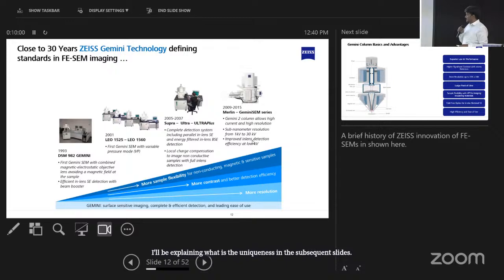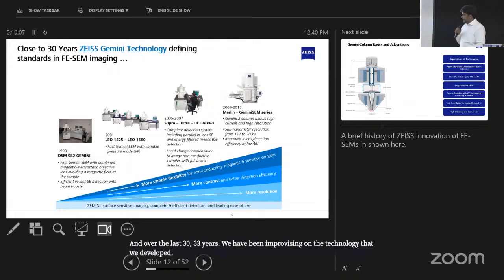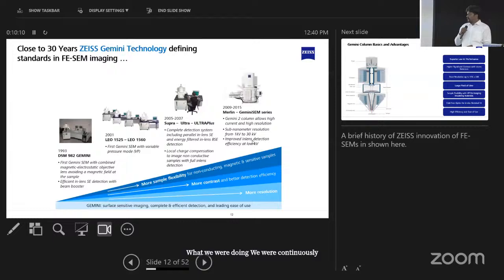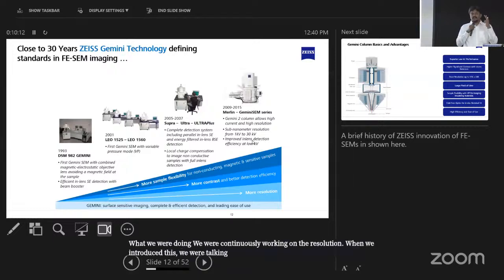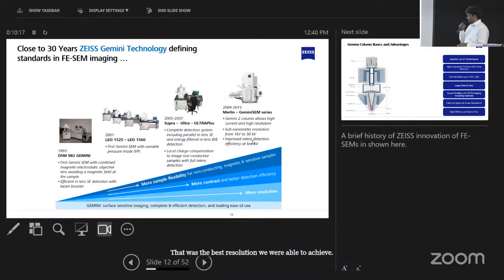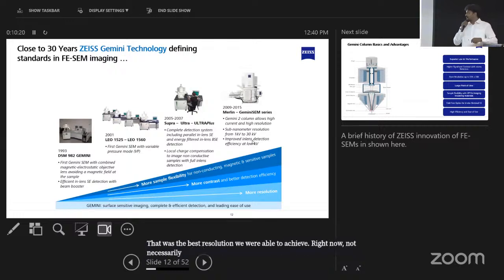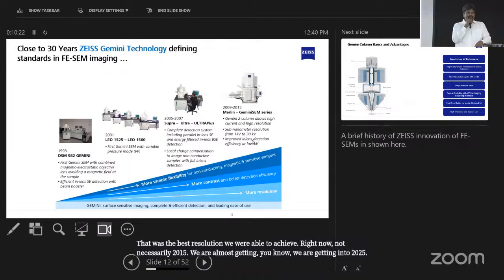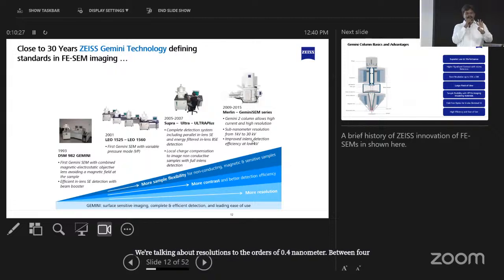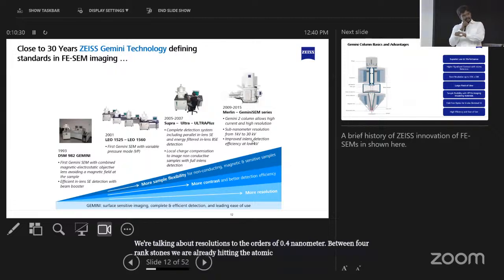Over the last 33 years, we have been improving on the technology that we developed. We were continuously working on the resolution. When we introduced this, we were talking about resolution on the order of 2 nanometers. That was the best resolution we were able to achieve. Right now, we are almost getting into 2025, and we are talking about resolutions on the order of 0.4 nanometer, which means 4 angstroms. We are already hitting atomic-scale resolution using the field emission scanning electron microscope itself. So that's the improvement we have been making with respect to resolution.